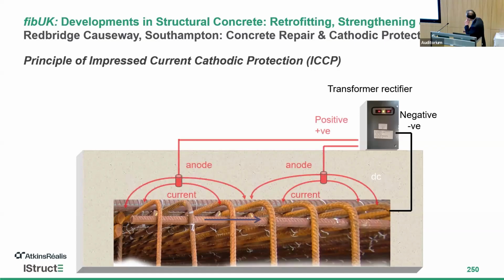So effectively, we are connecting the negative side of the DC power supplies to the reinforcement, and we're passing the current using inert anodes. It could be titanium or conductive coating, etc. And the current is flowing from the anode, which is the positive side, to the reinforcement and back to the power supply. Effectively we are shifting the half-cell potential of the steel to the safe and immune zone.